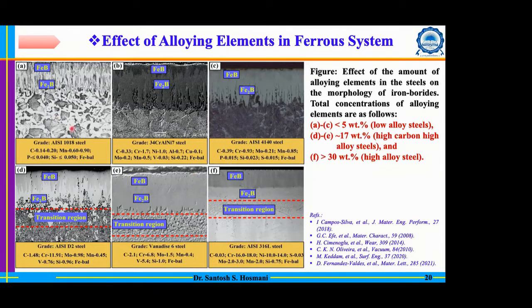You notice especially that in the case of low alloy steels, the morphology is more or less a sawtooth morphology. However, as you go to the medium or high carbon, high alloy steel range, at about 17%, you can see the FeB and Fe2B. From the color contrast, FeB appears darker compared to Fe2B, so you can distinguish them. The morphology of Fe2B is more or less smooth. It is not really appearing like a sawtooth. Some sawtooth appearance is there, but it is not as sharp as in low alloy steel. But the FeB morphology is still a very sharp sawtooth morphology.